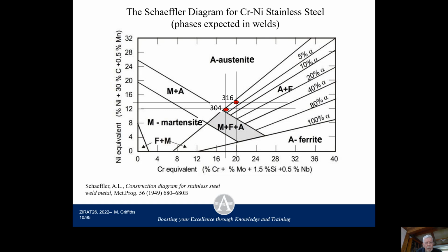I will be talking about different types of martensite, so we'll just leave that aside for right now. The important thing to know is that even in what are ostensibly austenitic steels, you should expect to find a little bit of alpha, depending on heat treatment and the thermomechanical history of the component.